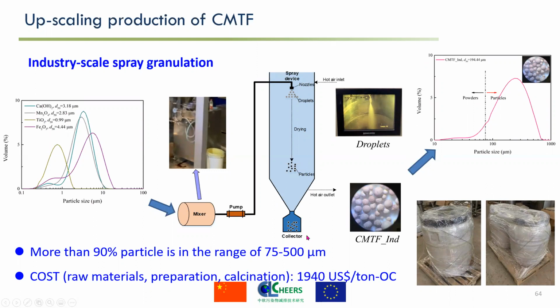Most of the collected particles are in the range of 75 to 500 micrometers. In the first stage, we produced 1,000 kilograms of particles. The total price, including purchase of raw materials, granulation, and calcination, is close to $2,000 per ton.